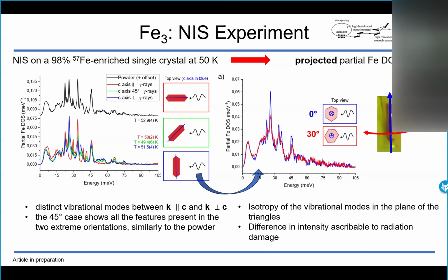And finally, we remounted the crystal in order to have the gamma ray wave vector always perpendicular to the z-axis, but with the possibility to rotate the crystal around its z-axis. So in this case, we could do the experiment with different orientations of the gamma ray in the plane of the triangles. Here, blue and red are two orientations differing by 30 degrees. We can see that the spectra practically overlap, meaning that we have an isotropy of the vibrational modes in the plane of the triangles.